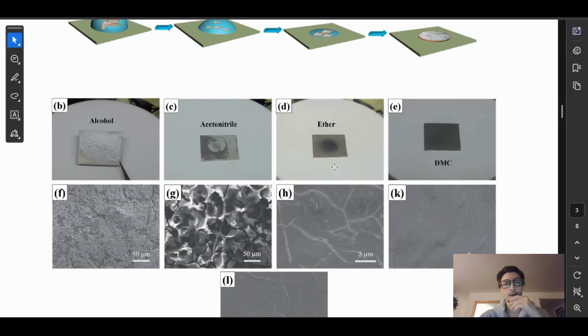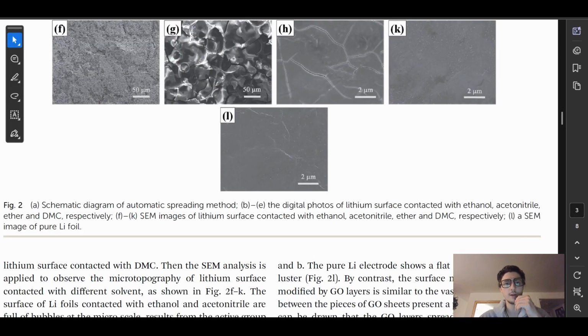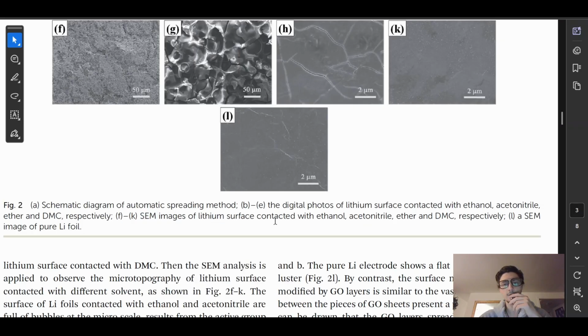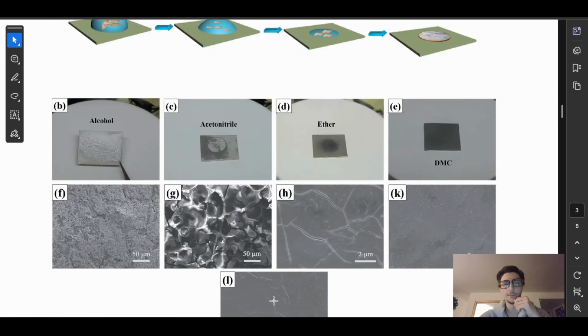So you can see they look a little different. I'm not sure why they look different. And right here underneath each, they actually have more images. Let's actually read what those are, F, G, H, K. This is right here, F to K. SEM images of the lithium surface contacted with ethanol, acetonitrile, ether, and DMC respectively. L, a SEM image of pure lithium foil. So this is pure lithium foil, right?